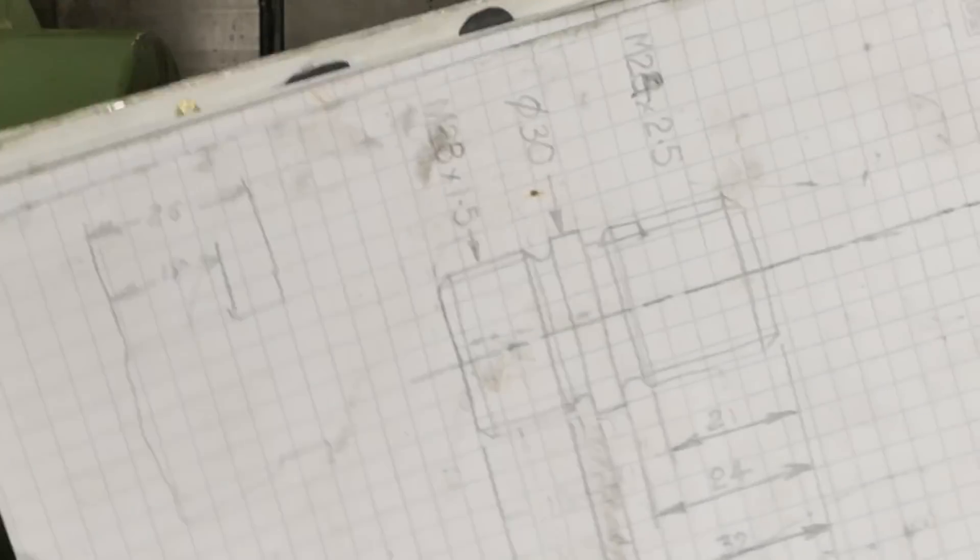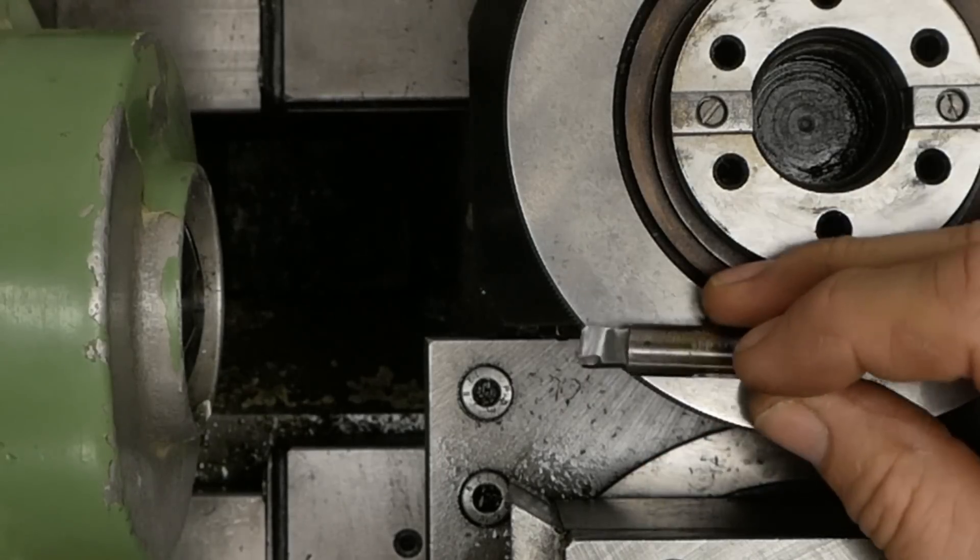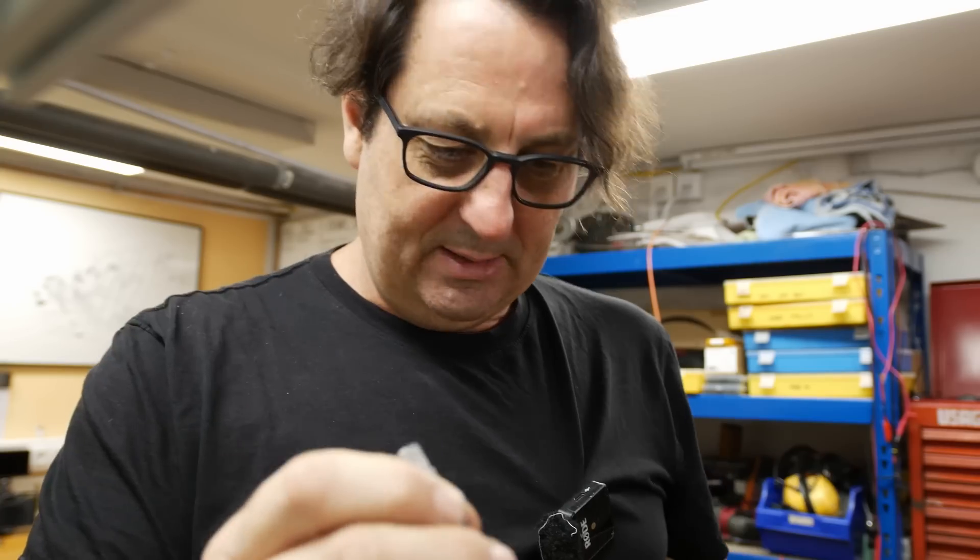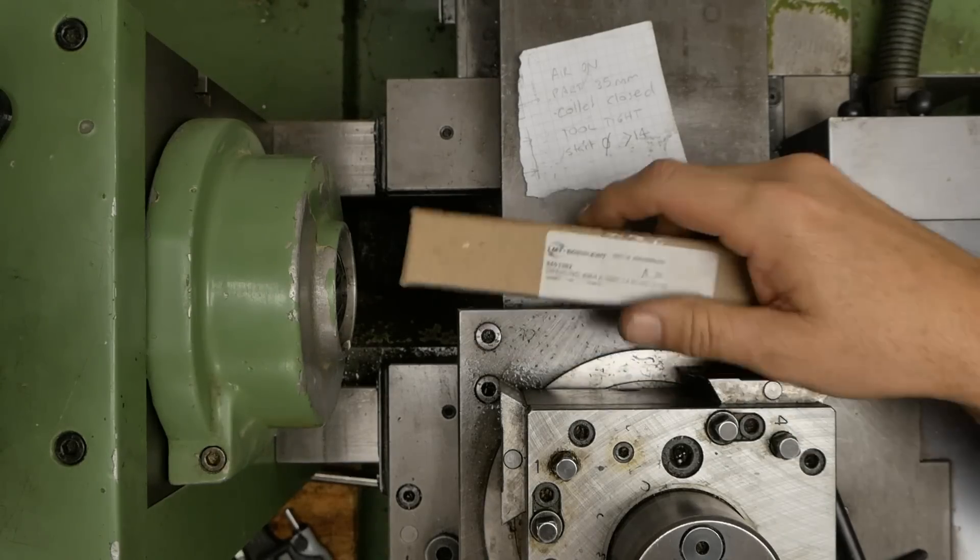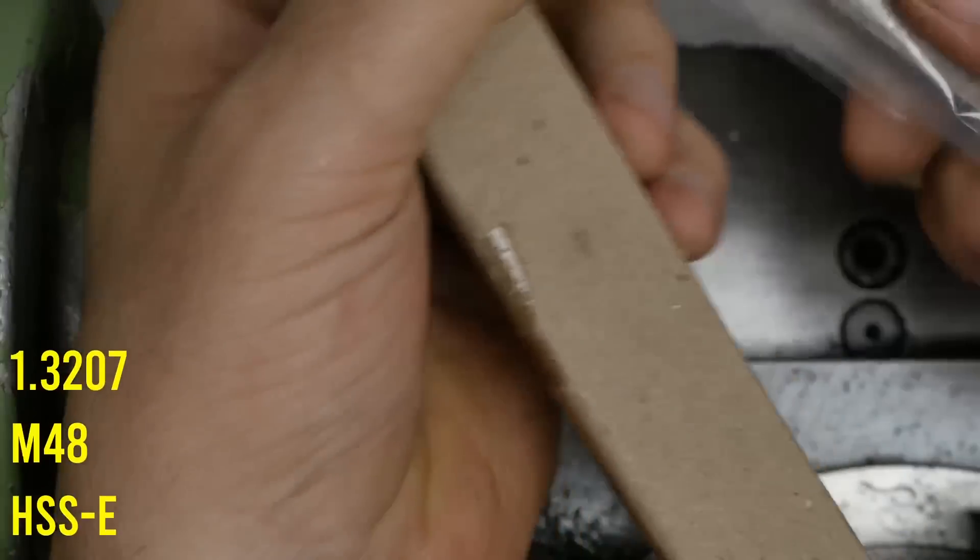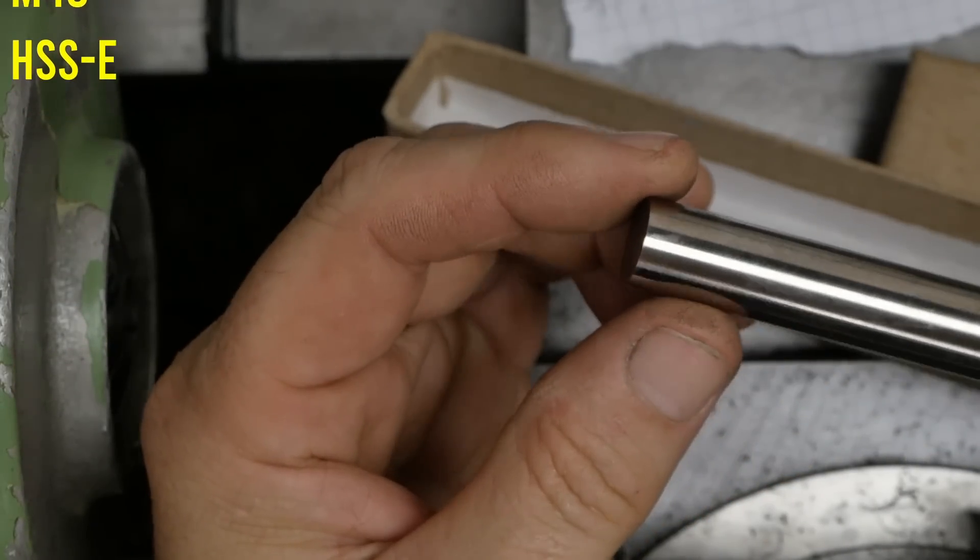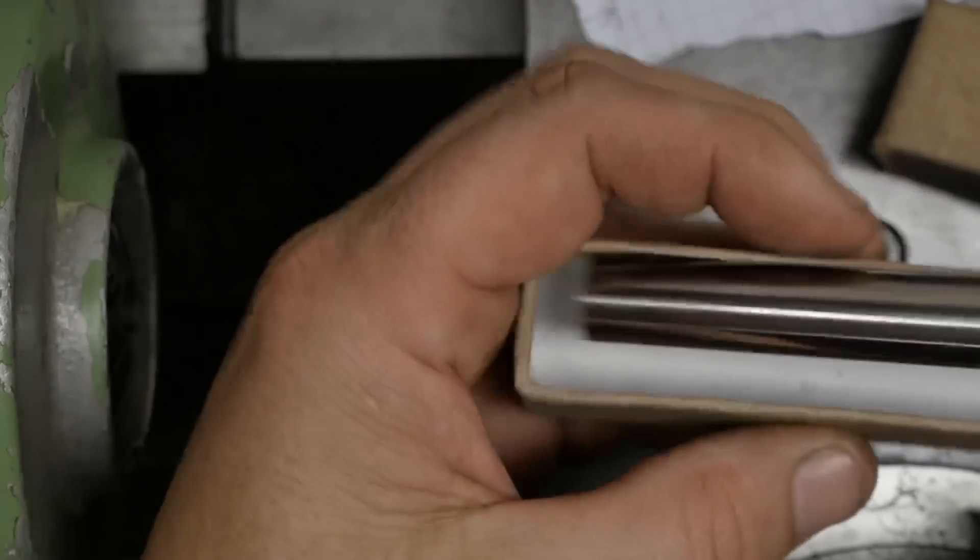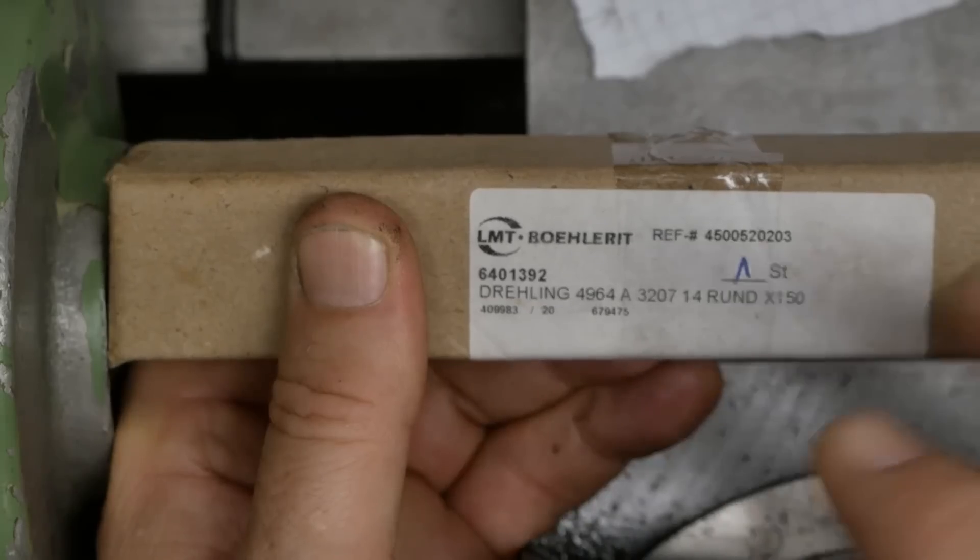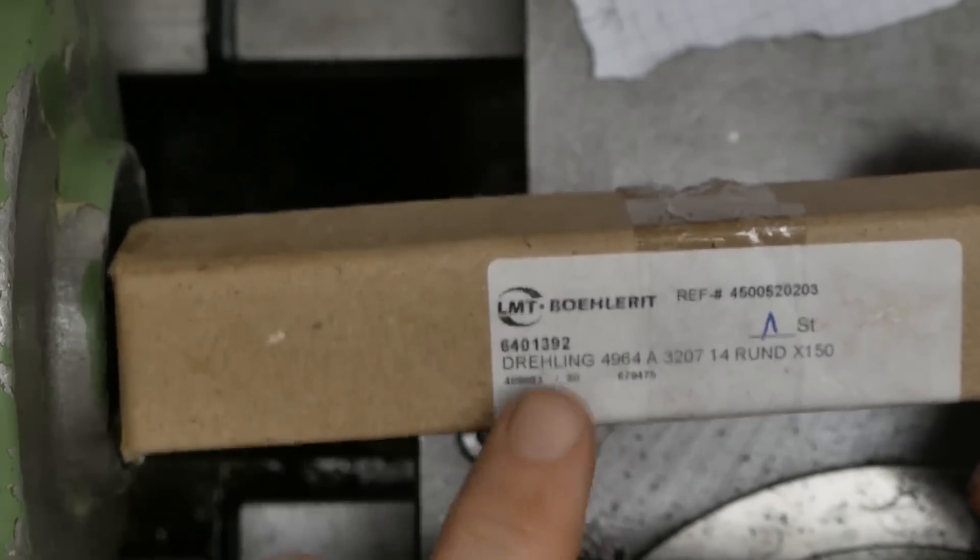So that's one of the things I've got planned. The reason we're here today is I'm going to need a hex in here, and to make a hex I need a rotary broaching tool. The rotary broach which Luke made for me takes 10 millimeter shanks, but the stock which was given very generously by Christian is this stuff: 1.3207. This is like a high-speed steel, it's known in America as M48 ANSI. It's got like 10% cobalt, 10% tungsten in it. It's supposed to be hard as buggery. I don't know exactly what heat treat these particular sticks of it are, but it seems to be normally heat treated between Rockwell C64 even as high as 67.